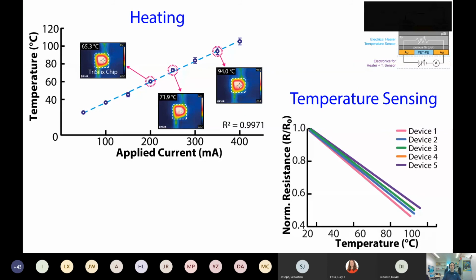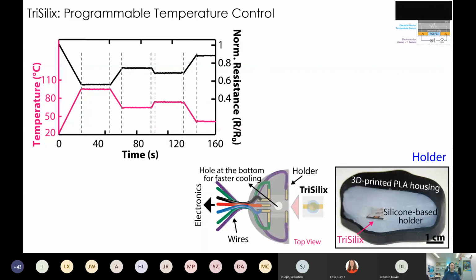And in terms of temperature sensing, within the range that we're interested in, approximately between 20 degrees and 100 degrees, the devices produce a linear temperature dependency, which is quite useful because nonlinear relationships are a little bit more difficult to handle. And we can cycle the temperature and then maintain it at a set temperature very easily. We have not optimized this, but as you see, the ramps are quite quick, which means that we can reach a set temperature very quickly and then do the reaction quickly too.